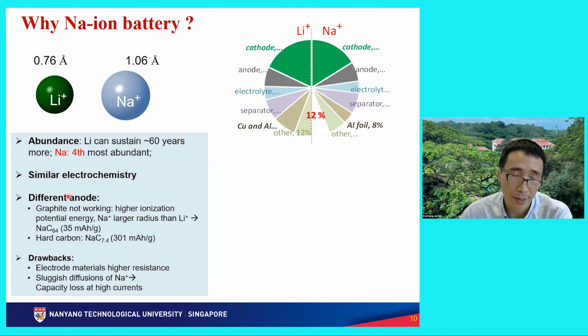The anode will not be graphite. Graphite is the commercial material for lithium batteries, but it does not work as an anode for sodium because of the high ionization energy, so that when the sodium ions go in, you will have a high energy barrier to intercalate. And also sodium has a larger radius than lithium, much larger compared to the interlayer distance of the graphite. So the corresponding capacity for intercalation is extremely small. Lithium is 370 something, right? But for sodium it's only 35.